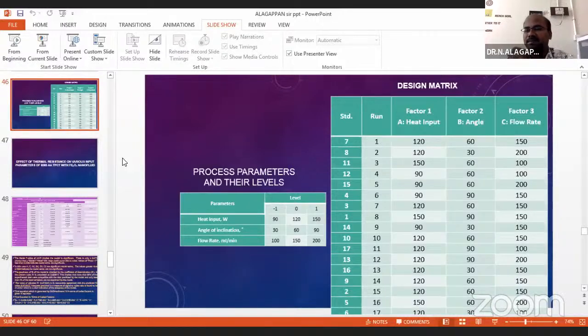So for the first reading, I am taking this value only. Because this is your first, 150, 90, and 150 is my first trial. I am going to take the reading, and the second trial will be 120, 60, and 150, which means I am giving the heat input as 120, angle 60, and flow rate is 150 ml per minute. Next slide, sir.